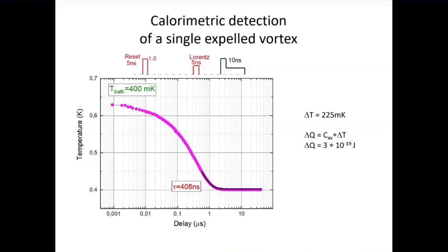You get 400 nanoseconds. At this temperature, it corresponds exactly to the electron-phonon relaxation time expected for overheated electrons. So if you overheat electrons in your system, then it takes this long for them to equilibrate back with phonons. So it remains in perfect agreement.